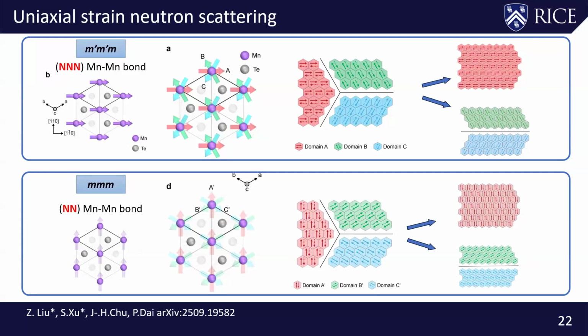And then if you try to detwin it, you can have 2 possibilities. The first possibility is that if you apply a uniaxial pressure in, say, the next nearest neighbor direction, you would expect to see the system change from this shape into either a single domain like this or 2 domains like this, by symmetry analysis. If it's this other magnetic structure, you would expect the same, except now the moment is rotated 30 degrees from the previous case. So our hope is that by doing an experiment with uniaxial strain, we can look at the entire reciprocal space, compare the intensity changes, and see whether we can truly detwin the sample from 3 domains to 1 domain, and therefore determine the magnetic structure of the system.